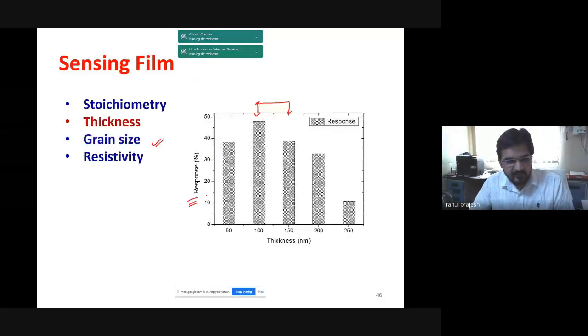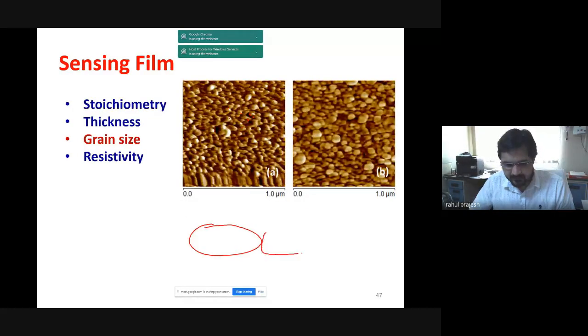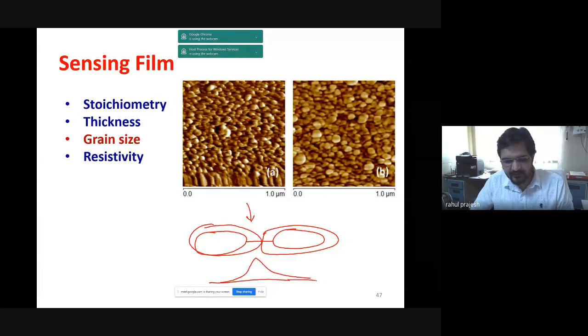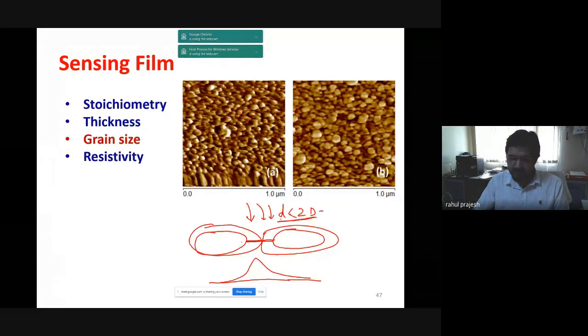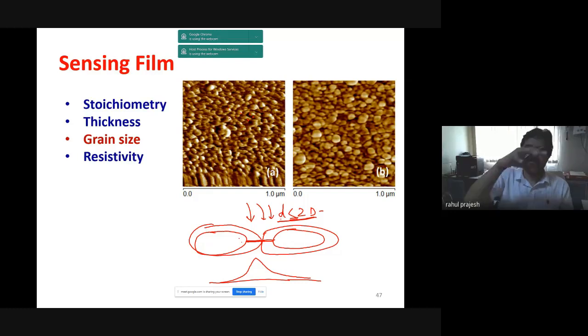As I told you earlier, these are grains, and if gas gets adsorbed on the surface, it gets depleted, and because of the depletion, there is a barrier increase. Barrier gets increased. So for the best sensitivity, while gas is adsorbing on the surface, this should be depleted completely. Complete depletion means this depletion width, like this 2D, and your grain size should be less than this 2D. If it is less than or equal to 2D, then your complete grain will be depleted. If it is completely depleted, that means the complete grain is taking part in the sensing phenomena. If the complete grain is taking part, you are getting the best response. So that's why grain size is very important.